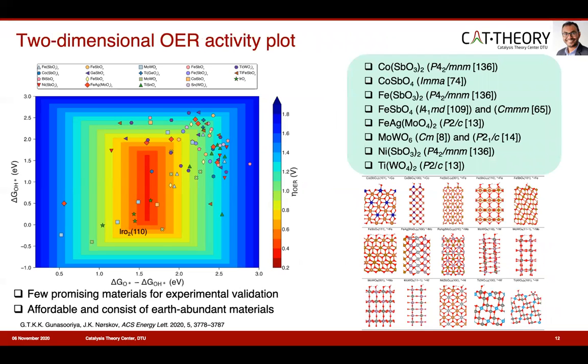In this 2D OER volcano plot, we use ΔG_O minus ΔG_OH and ΔG_OH as descriptors to plot the OER overpotentials. Based on the current understanding, the optimal OER catalyst site has a ΔG_O minus ΔG_OH descriptor value in the range of 1.5 to 1.7 eV, based on the conventional mechanism and scaling relations. In the color scheme, red means it's a good catalyst with low OER overpotential, and blue means it's a lousy catalyst. We notice that there are a few good catalysts, but most of them are pretty lousy. Cobalt antimonate, you can see here, iron antimonate, iron silver molybdenum oxide, molybdenum tungsten oxide, nickel antimonate, and titanium tungsten oxide. So these catalysts are affordable and consist of earth-abundant materials.